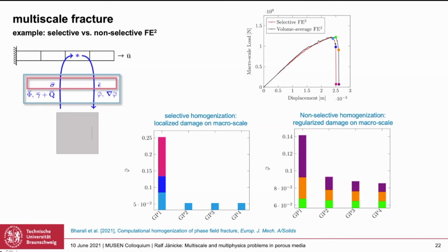And what we were interested in is to see how this localization occurs. Here on the left-hand side, you see the evolution of this damage for the red curve. We're starting with this light blue state where damage increases only in one element, the one with the notch. Then if you follow this curve into the collapse, into the light purple, we see that the damage is only growing in one element. That's a classical local damage model, actually.